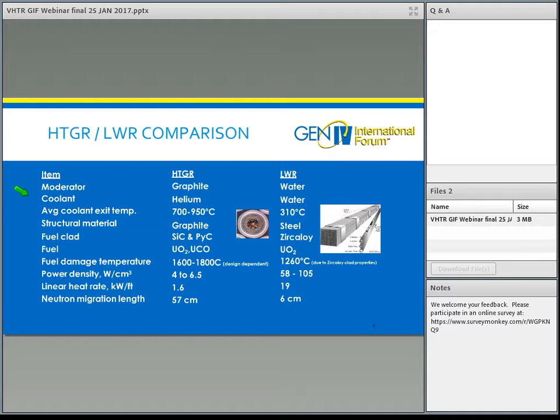Just again, looking at how the reactor is constructed leads to a difference in the power density. The high temperature gas reactor has a very dispersed core structure, and the power density within that core is quite a bit lower than a light water reactor, where in the fuel elements the power density is very close and very high. That leads at the same time to the linear heat removal rate being much lower in a gas reactor. Over the same distance in the core, you would need to remove a lot more heat at any given time from a light water reactor.